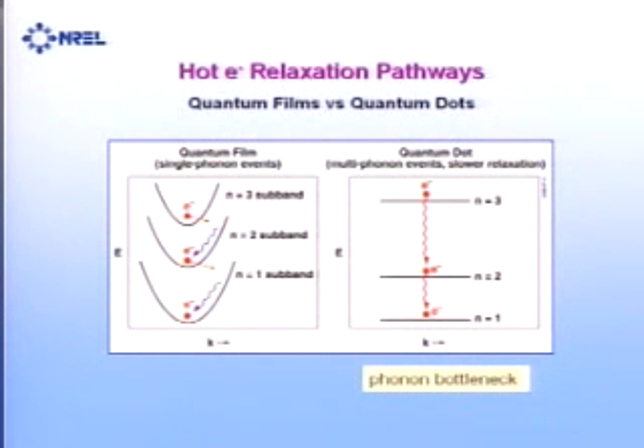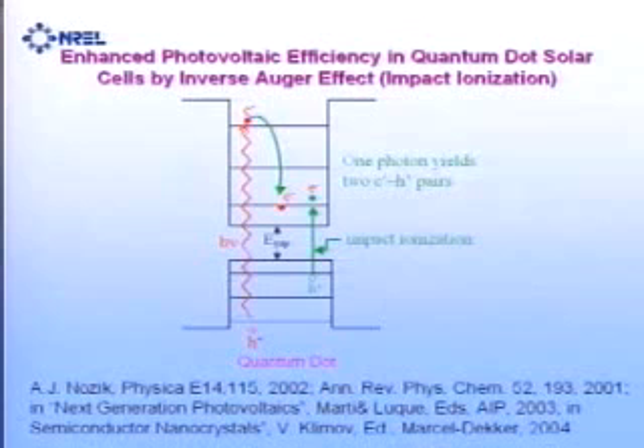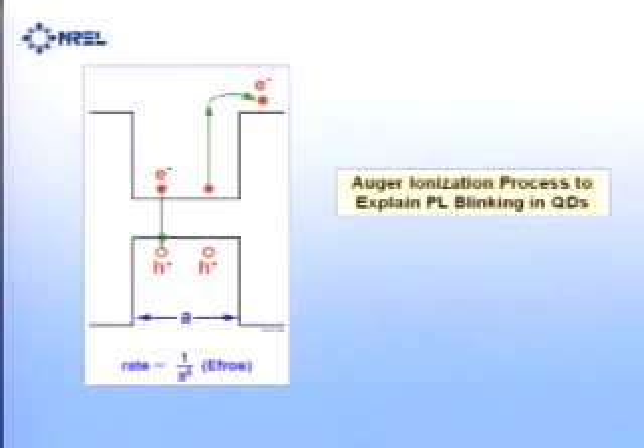And one of the reasons why the relaxation is slower in a quantum dot is that because you have discrete states and you want to go from one level to the next, because of the small size, these levels can be separated by several hundred meV, which is 5-6 times the phonon energy. So you need many phonons in order to go from, say, n equals 3 to n equals 2. So that's called the phonon bottleneck. And so the idea is that you're going to slow down the cooling because of the quantization. That'll allow a higher probability for doing this carrier multiplication.